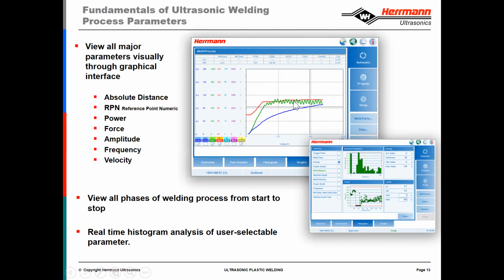I would maybe profile the force a little bit higher, because what's happening is that the energy director is a triangular shaped bead, and initially, when it's at the point of the energy director, the melt initiation is pretty easy to achieve. But as you consume a larger cross-sectional area of that energy director, as shown in that previous video, typically more melt is consumed and we have to push harder.